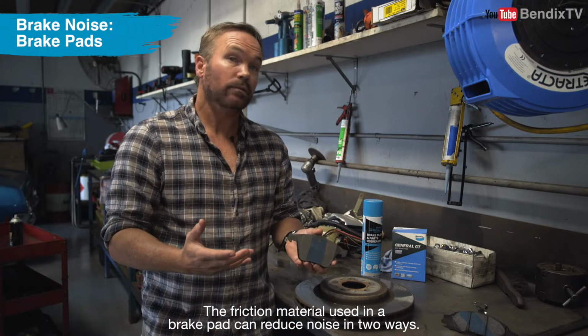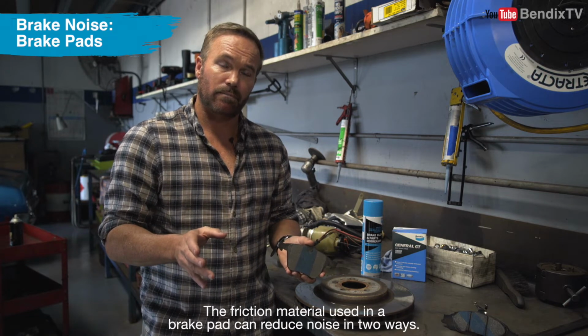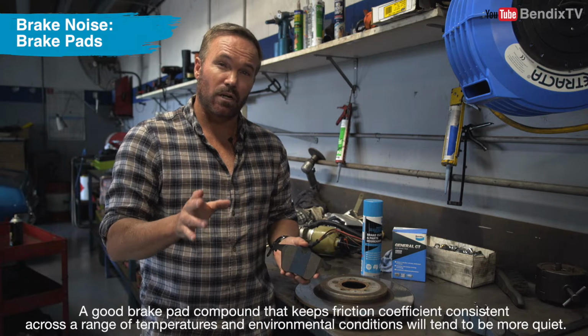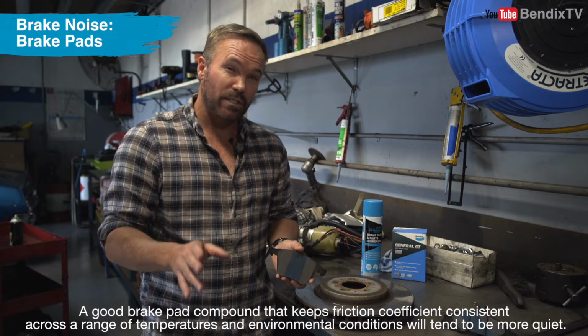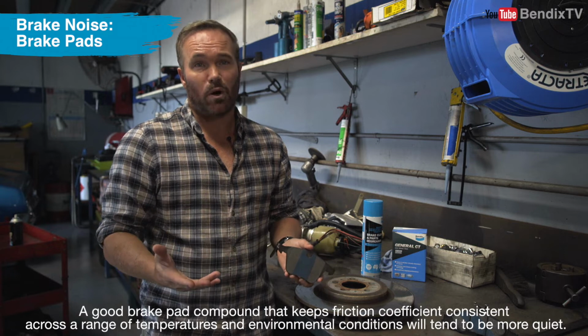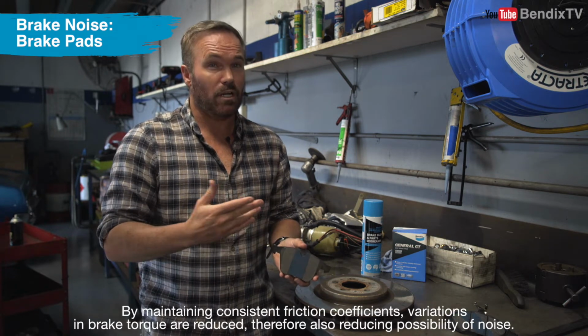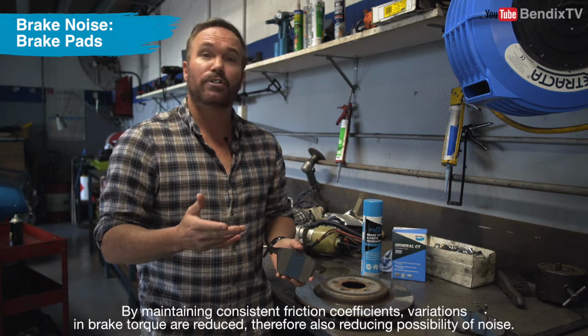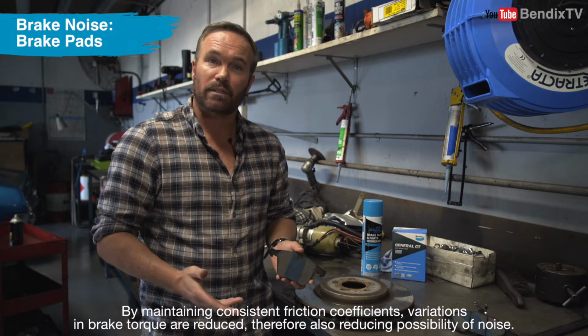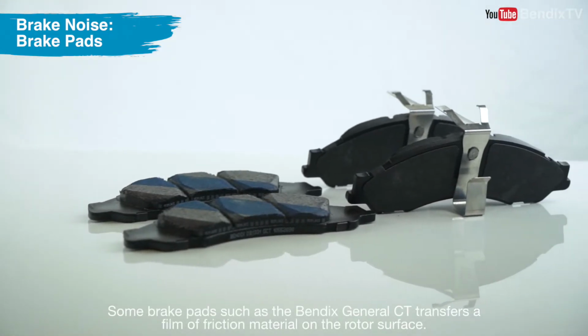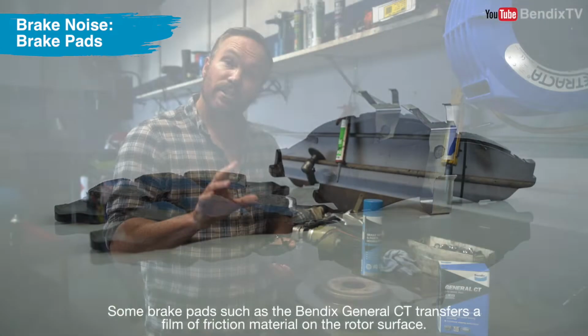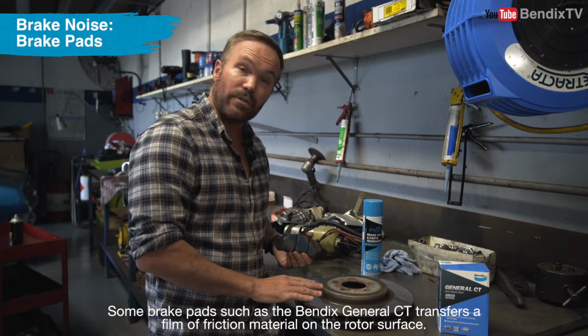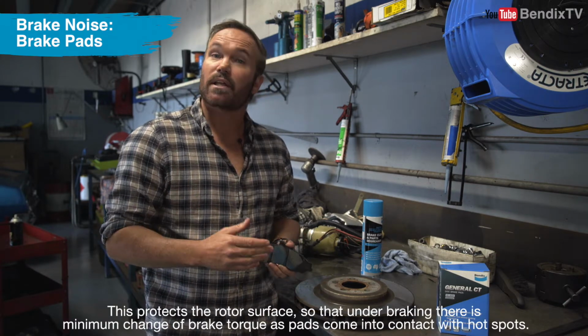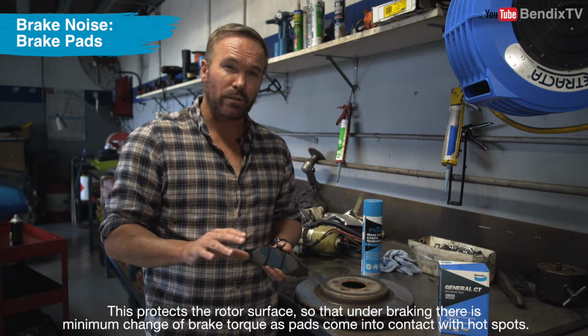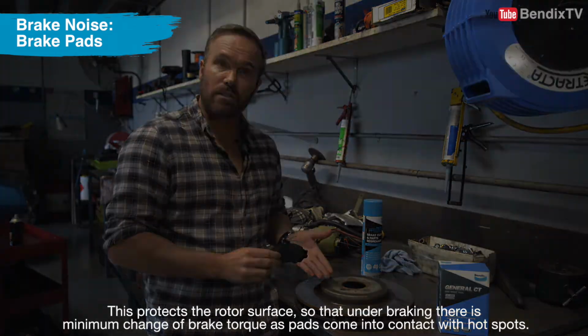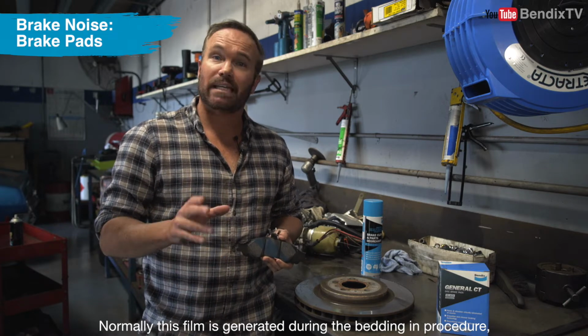The friction material used in a brake pad can reduce noise in two ways. A good brake pad compound that keeps friction coefficient consistent across a range of temperatures and environmental conditions will tend to be more quiet. By maintaining consistent friction coefficients, variations in brake torque are reduced, therefore also reducing the possibility of noise. Some brake pads, such as the Bendix General CT, transfer a film of friction material onto the rotor surface. This protects the rotor surface so that under braking there is minimum change of brake torque as pads come into contact with hot spots. Normally this film is generated during the bedding in procedure.